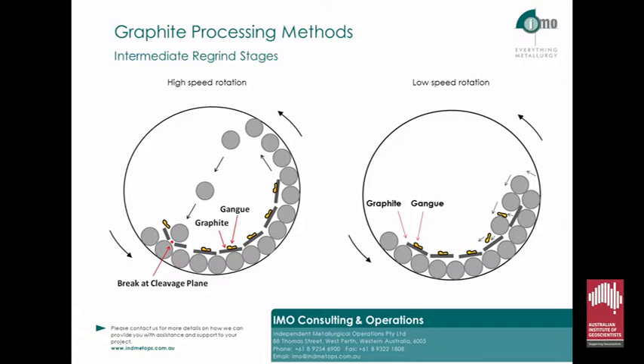When scaling up this process, it's important to consider the size of the mill and media required. For if it's a traditional horizontal mill, a lower than critical speed and ultimately energy input is required. The mill on the left would typically run at about 70 to 75% critical speed, whilst the mill on the right may be down to only 20 to 25% critical speed.